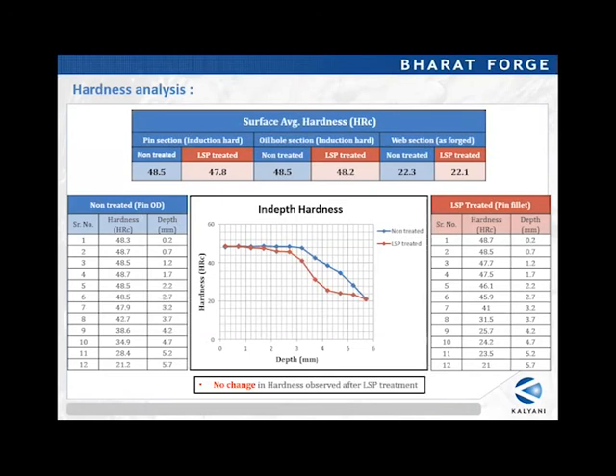Now we have measured the in-depth hardness of the material at various depths, and both the graphs are plotted. Red is showing the LSP treated and blue non-treated. Here also you can see that there is no change in hardness observed due to LSP treatment.